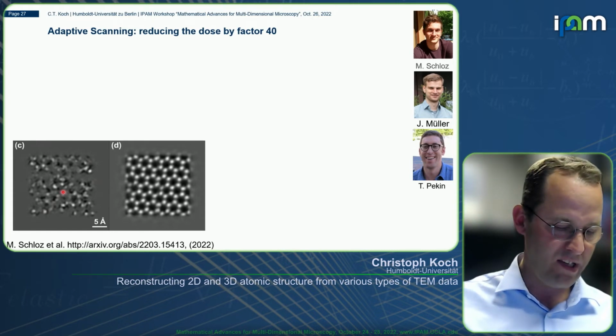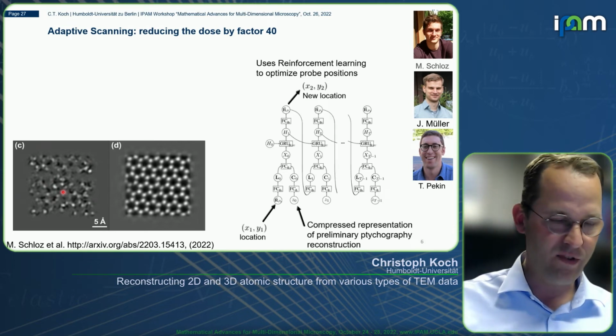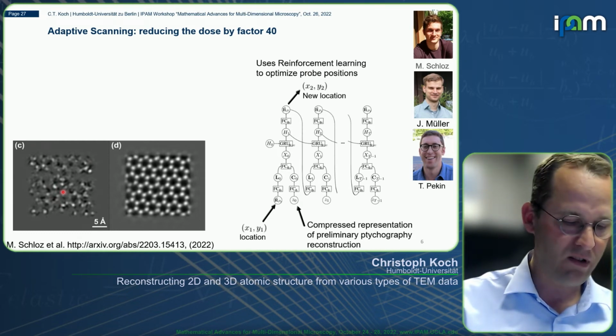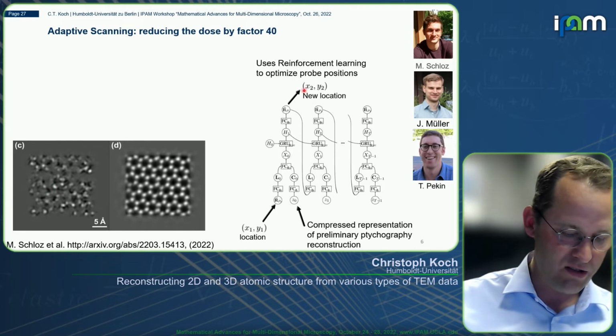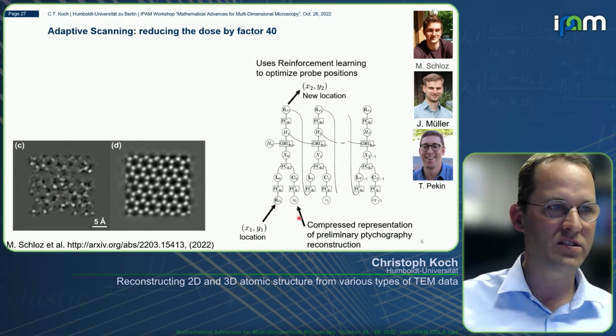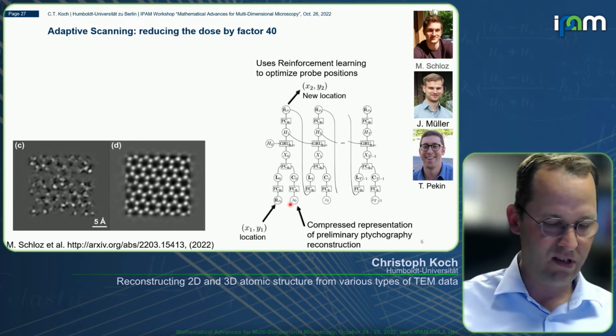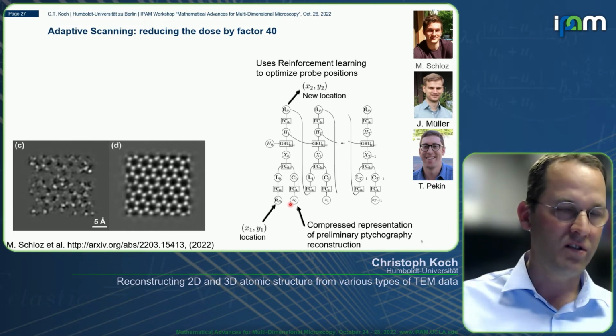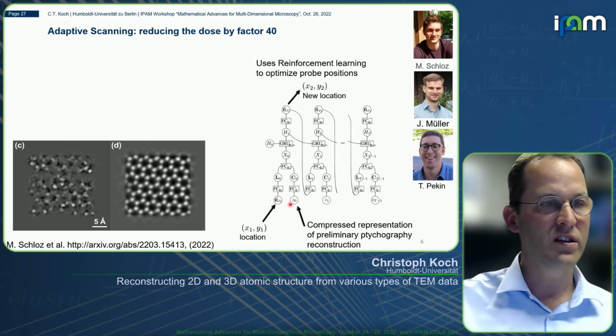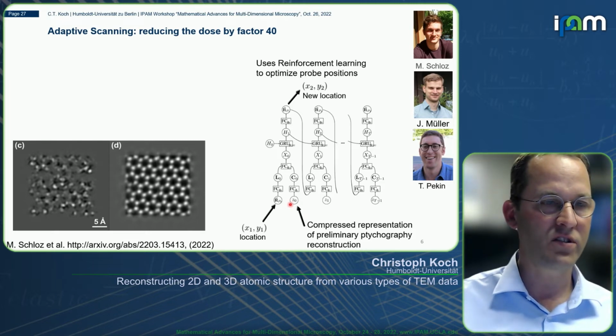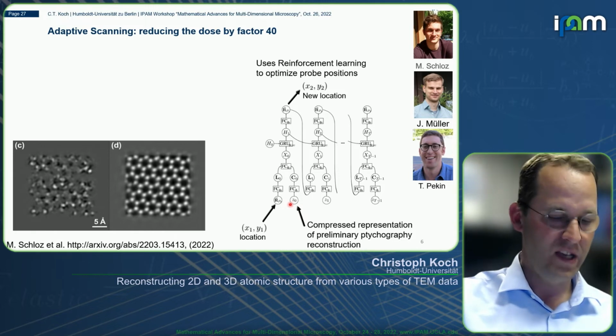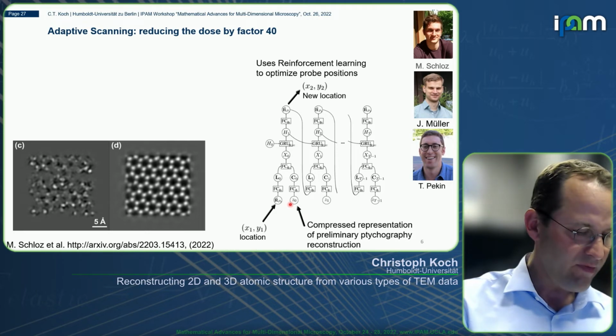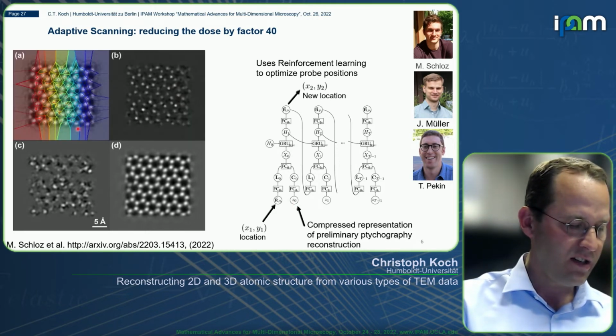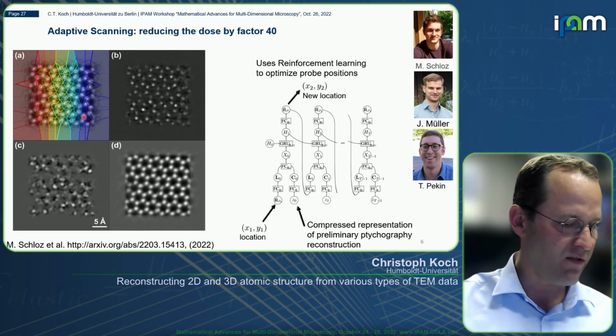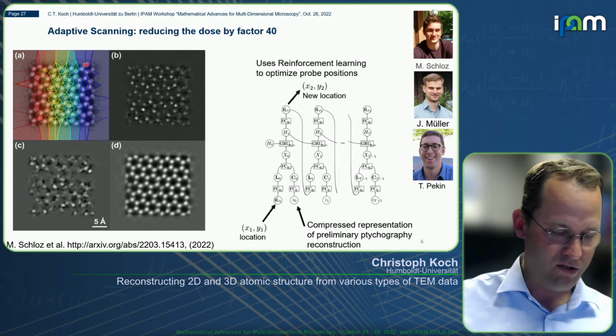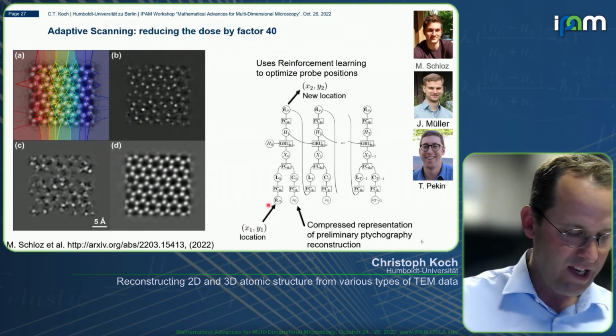What Marcel has done is train an artificial neural network, using a reinforcement learning scheme, feeding in the position of the beam but also a compressed, auto-encoded representation of the reconstruction with the current estimates of probe positions, and trying to predict probe positions that give an improved reconstruction. The figure of merit he was trying to optimize was the contrast in the reconstruction over the current estimate. He came up with a scheme where he first had a random scan of some area. From the initial reconstruction over this first patch of probe positions, he then fed these, together with the reconstruction and the probe positions, into this reinforcement learning scheme and had it predict.